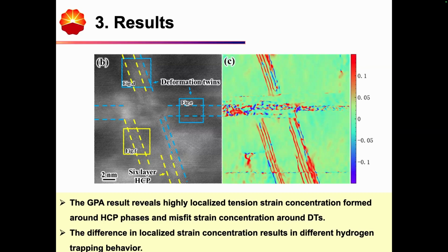All this trapping behavior will cause some repartitioning of hydrogen beneath or near the intergranular crack, causing very high localized hydrogen concentration and promoting the propagation of the intergranular cracks.